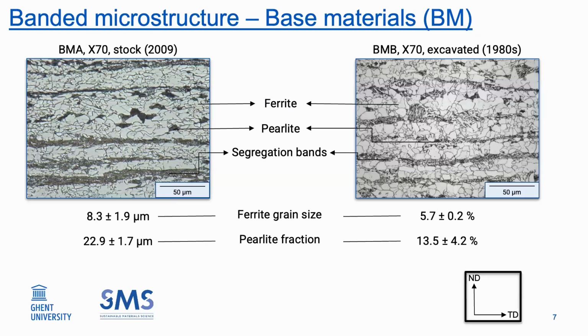The micrographs here are taken from the pipeline middle region along the rolling direction. Both these materials have a highly banded microstructure throughout the thickness of the pipeline, consisting of ferrite and pearlite. In the middle thickness, we also see the presence of segregation bands, with lots of inclusions present there due to the segregation of elements. The difference between the BMA and BMB is based on the ferrite grain size and the pearlite fraction, both of them being higher for the stock material as compared to the excavated one.